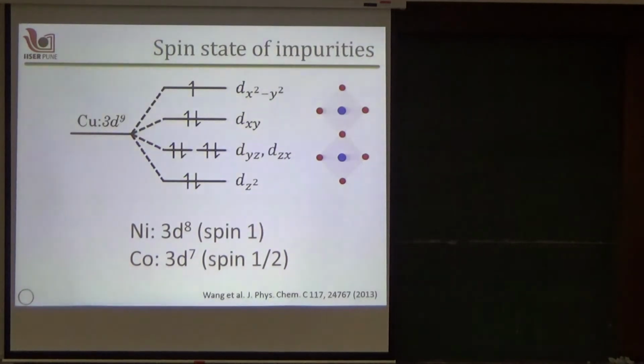Copper 2 plus has a spin which is nearly isotropic because the orbital angular momentum is almost completely quenched, but that's not true for cobalt ions. There are detailed theories for that, done maybe in the 60s, and to be very frank, I don't understand those theories. Those are crystal field theories, but one can show rigorously that with cobalt one ends up with a strong on-site anisotropy.